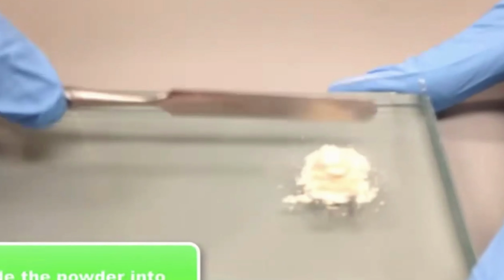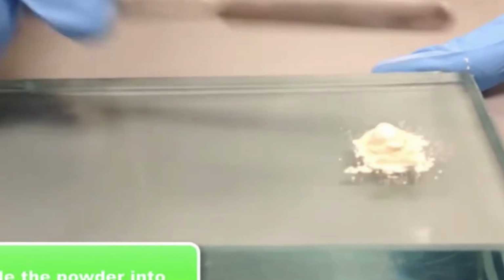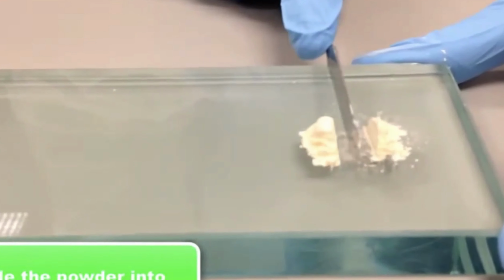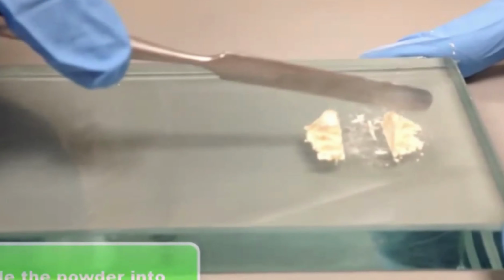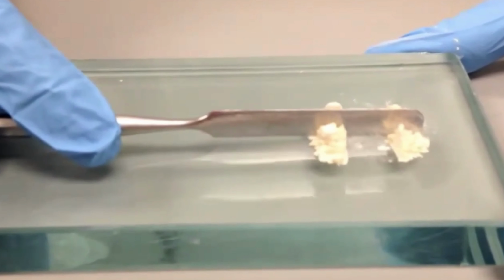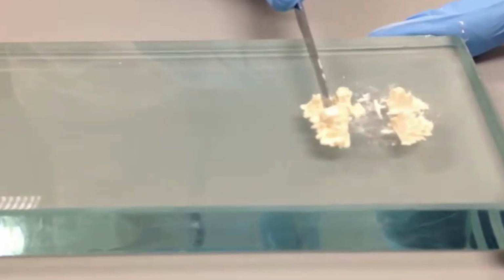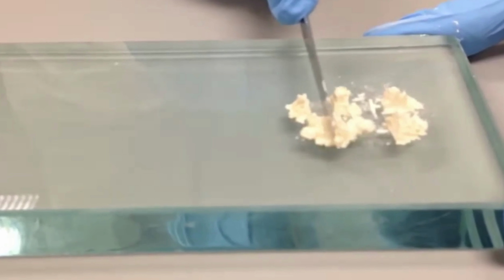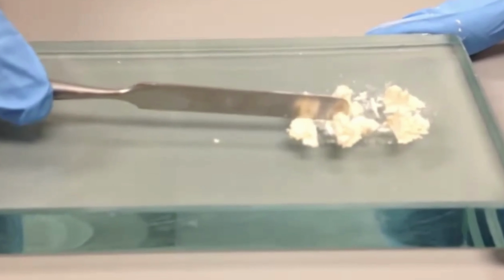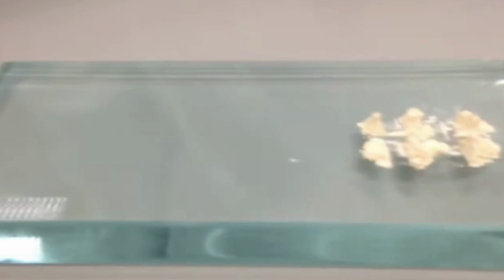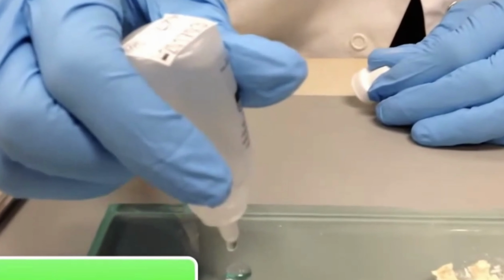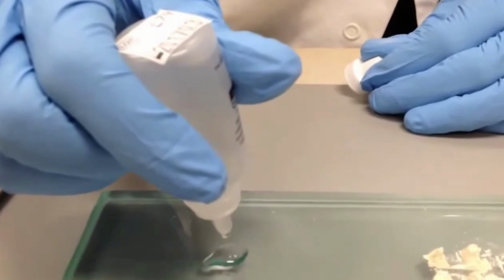And now you'll see she's dividing the material into about 6 fairly equal portions. You can start by first dividing them into 4, and then she'll take some extra from one of the piles. So now that you have about 6 piles to go with, the next step is to empty 6 drops. You want to turn the container completely upside down and let 6 equal sized drops fall onto the slab. And now you're ready to mix.